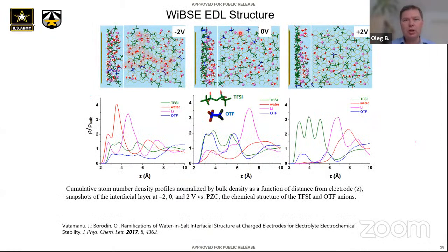Right? So we're going to start with the potential of zero charge and look at the side view and top view of the inner Helmholtz layer next to the electrode. What we do observe is that TFSI and triflate have a relative enrichment, which is good, right? I mean, water gets pushed away. There is much less water here. We do observe that they have proximity to lots of lithiums in both places. So the lithium is available to remove fluorines from triflate, remove fluorines from TFSI, and also decompose TFSI, and have an anion-based SEI forming as opposed to hydrogen evolution.